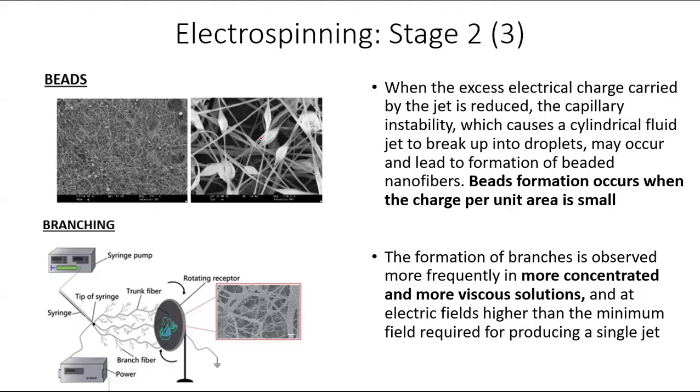It is because if you don't have the necessary electric charge, this continuity will be broken. So therefore what happens? There will be droplets forming, and then these droplets will solidify as beads.